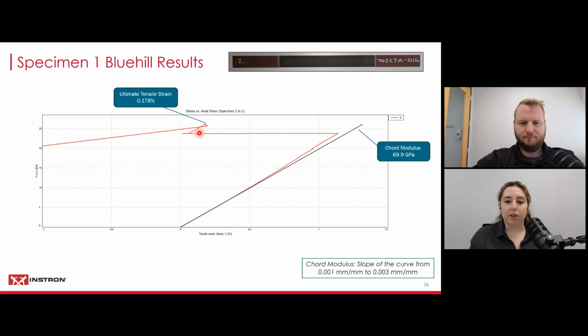So really, with this kind of test, I probably want to remove the clip-on at around 0.5% of strain, and then just let crosshead displacement take over. And crosshead displacement is absolutely acceptable in terms of end of test criteria, and we'd be able to have the correct ultimate tensile strain with the correct force.